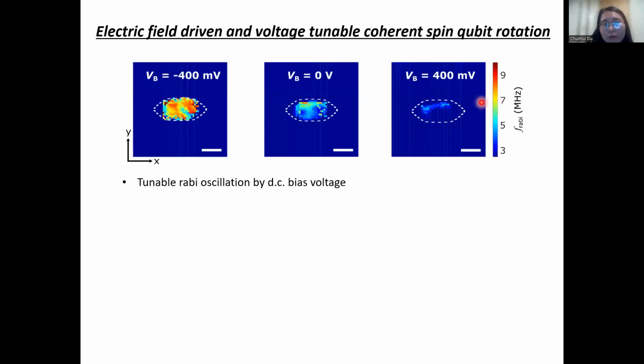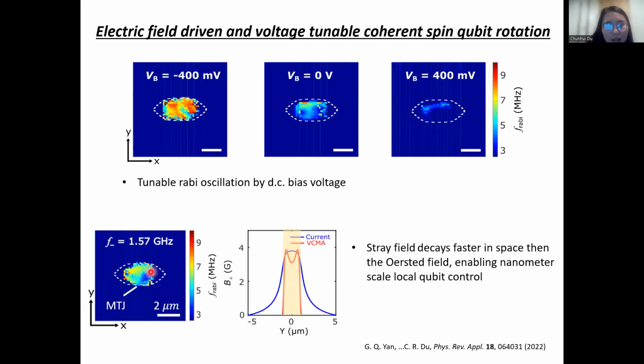And we can also use our wide field imaging technique to image the microwave field generated from these hybrid devices. We can see that the oval shape is the boundary of the magnetic tunnel junction. And we can see that the microwave field generated from the junction is confined very locally, and only appears on top of the junction. We can also turn on and off the microwave generation by using the bias voltage. If we take a line cut along the width direction, we can see that the microwave field decays very locally in space. So it decays much faster in space than the Oersted field generated from the current in a strip line structure. So this demonstrates that our hybrid device can enable nanometer scale local control and voltage control of the NV spin qubits.